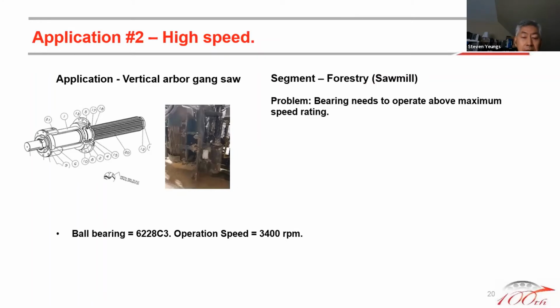Typically, in my past few years, there are a few applications where the bearings actually are needed to run above what we refer to as the speed rating. In this particular application, it's a vertical arbor gang saw, almost like a spindle with two bearings. A 6228 is a ball bearing, and the operating speed is 3,400 RPM. But when you look at the older catalog, the speed rating for grease is only 2,200, and for oil, it's only 2,800. How can that be possible?